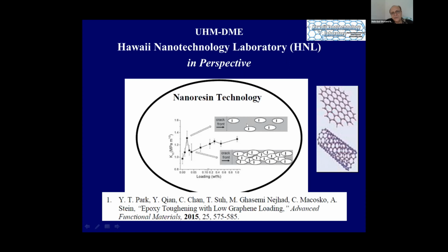0.04%, then beyond that, those functionalized graphene will get close to each other. So the coalescence in this sense, and then they don't have that effect, so it's kind of an agglomeration, so the property drops. And this happens because of the larger inclusion and also van der Waals forces. But then when we change the mechanism from this well-dispersed nanomaterials to this coalescence, when the property drops, then further increase of nanomaterials will still increase the property. The reason is that the crack will go through more nanomaterials. So this we introduced in this journal, this microcracks coalescence mechanism.